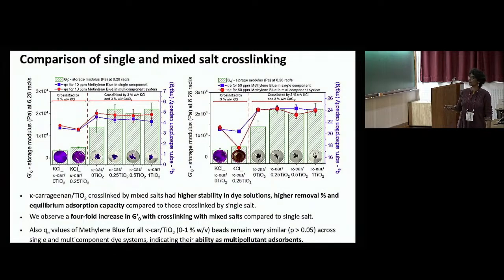And the major conclusion is that if I have to make these beads, I need to use mixed salts to give higher stability and higher removal percent. So these beads are stable, they don't disintegrate, they don't dissolve in the water. And of course, the G prime has an effect with the salt addition, not too much with the addition of the titanium dioxide. And these are the equilibrium adsorption capacities which we measured, which remain very similar across the single